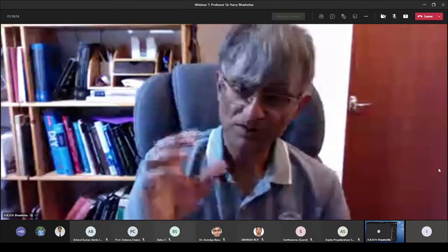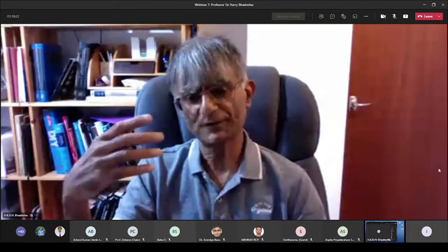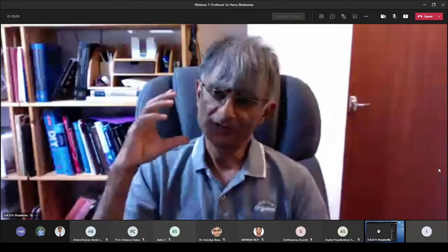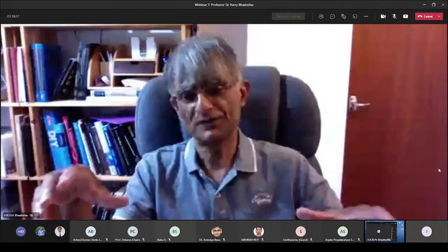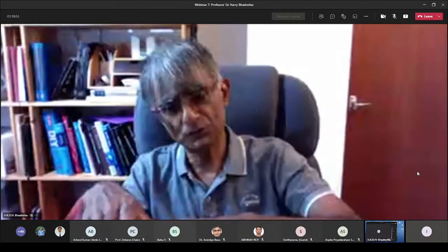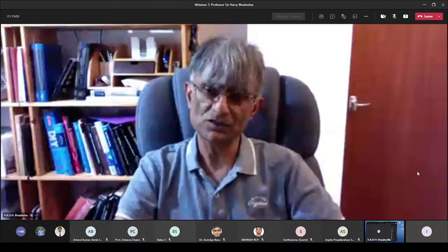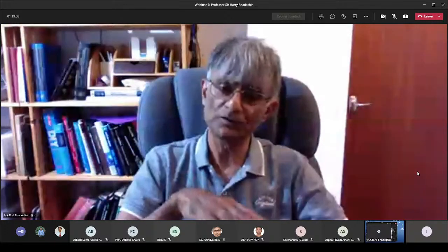So, this is actually a very complex question. Thank you very much for that. I have a colleague, Jai Jaiswal, who has a lot of experience in industry and in the rail industry. The sort of things that you need to consider is what sort of track you are interested in. Does it involve a curve? What is the radius of the curve and so on? The carbide-free Bainitic rail doesn't perform too well on a highly curved section of the rail. There you have to use pearlitic rails or other variants. There's actually a huge variety of commercially available rail steels for different kinds of scenarios on the route itself.